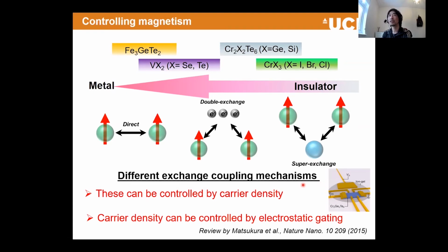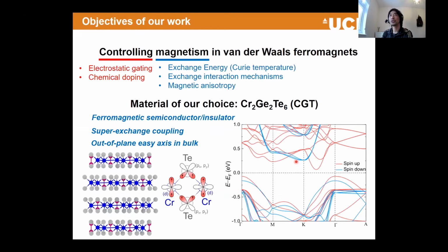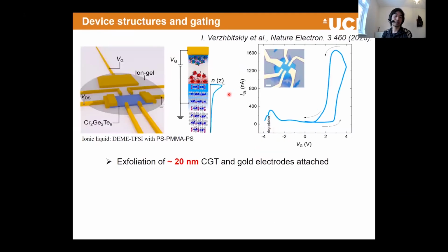So the material that we use is chromium germanium telluride. I'll just call it CGT from now on. This CGT is a ferromagnetic semiconductor. You can see the gap here. Again, this is a layered material, and the exchange coupling is through the tellurium atoms, so this is a super exchange mechanism. We try to gate these materials, as Antonio already explained a little bit, and see how the magnetism changes depending on the gate voltage.